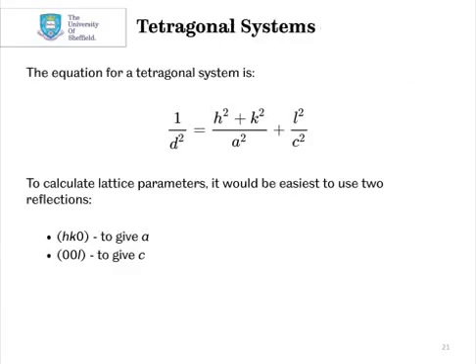The equation for a tetragonal system is a little bit more complicated. 1 over d squared equals h squared plus k squared over a squared plus l squared over c squared. So we have a separation here of the h, k, and then the l Miller indices. So if we want to work out the lattice parameters from this, we're going to need an hk0 type reflection to give a, and a 00l reflection to give c. So for example, you might look for a 001 to find out what c is, and then a 110 to find your a lattice parameter.